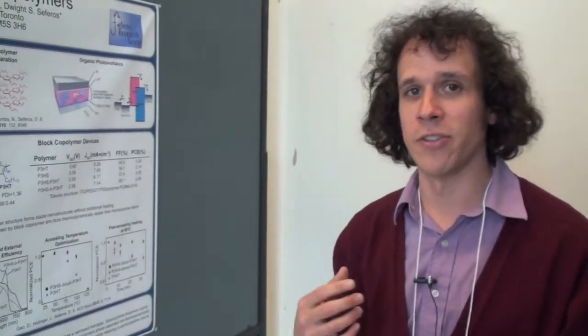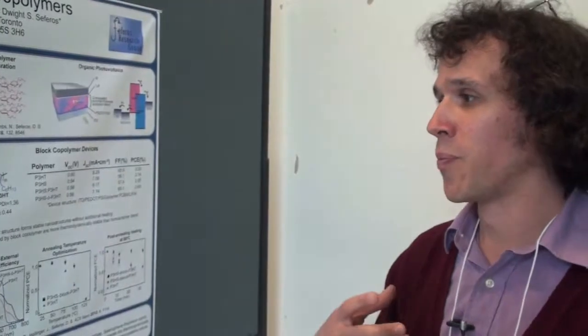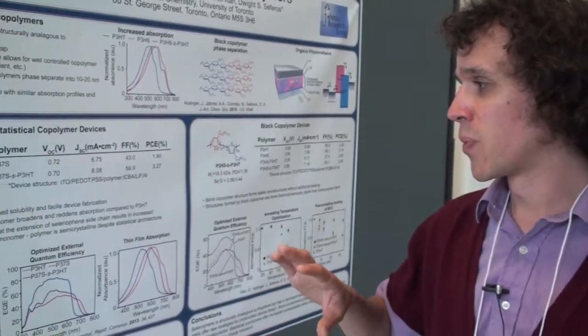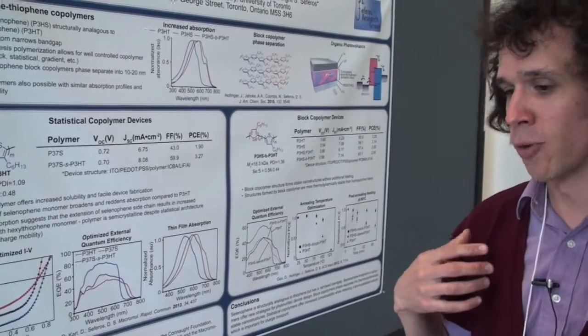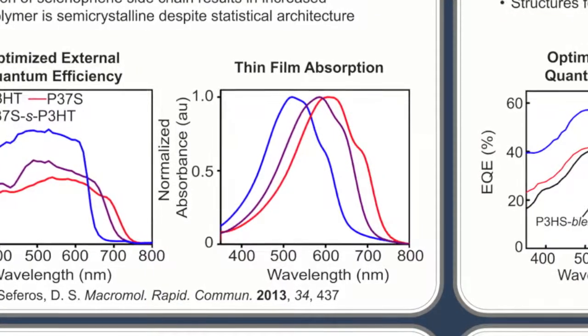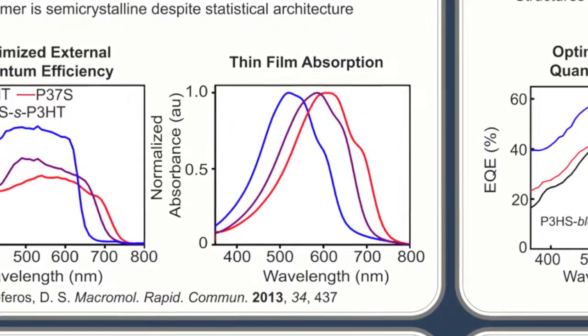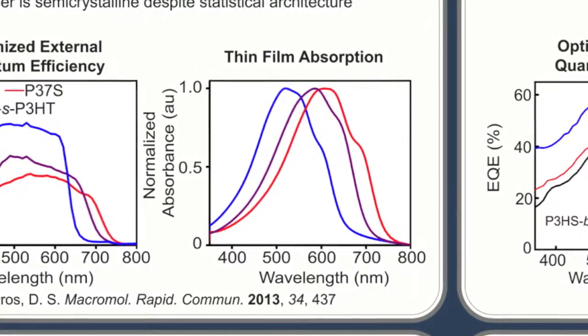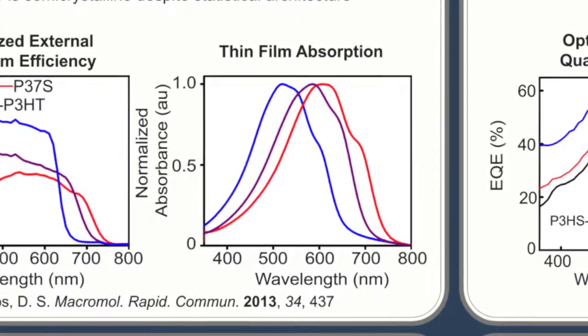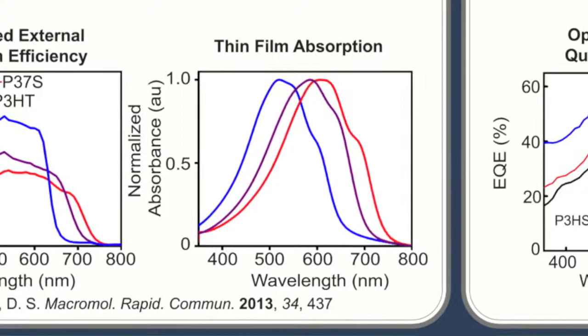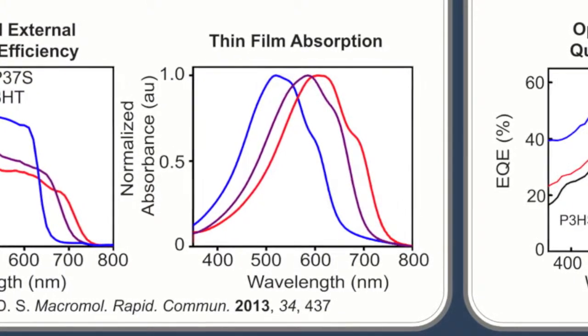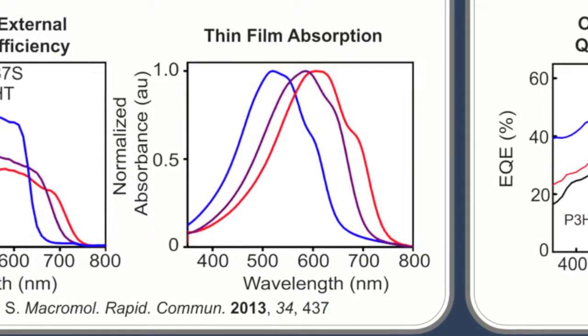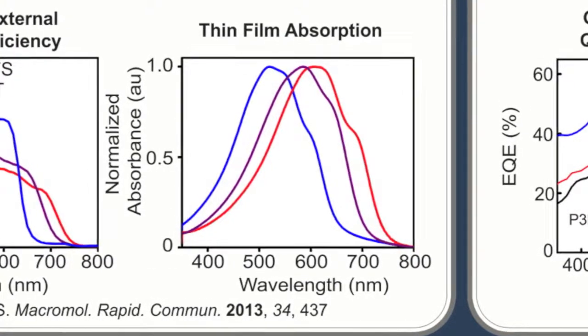Another avenue that we've investigated is generating statistical copolymers. So, polymers where selenophene and thiophene units are distributed randomly along the backbone instead of two distinct blocks. And what we found in this case is that we still have the overall reddening of the absorption profile, as you can see with the statistical absorption profile in thin film is here in the middle. So we still have that overall reddening of the absorption compared to P3HT. And we still have, despite this random distribution of monomers along the chain, a semi-crystalline nature, which is really important to have that pi-pi stacking in order to facilitate charge transport.